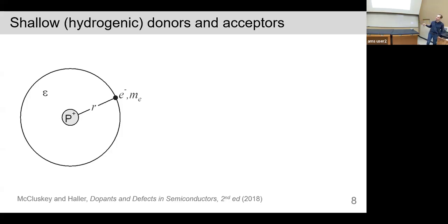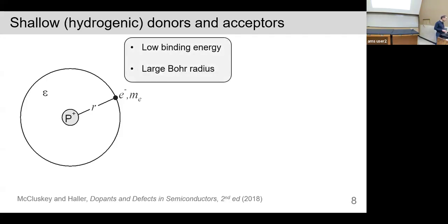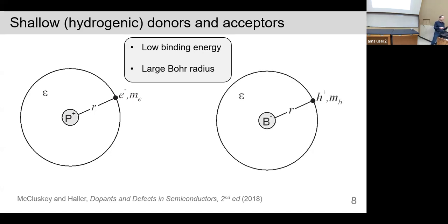You have a positively charged phosphorus, and the negatively charged electron goes around. You have an effective dielectric constant that screens the electric field. So instead of 13.6 eV binding energy, you get something like 20 millielectron volts. So it's much smaller binding energy. So low binding energy. And what goes along with that is a large Bohr radius. Other than that, it's essentially like the hydrogen atom.